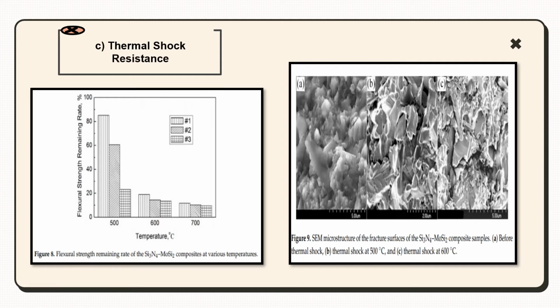As demonstrated in this figure, microcracks could be clearly observed when compared with the samples without thermal shock experience. In addition, the quantity and size of the microcracks increased with increasing thermal shock testing temperatures, which resulted from the internal stresses due to the thermal expansion mismatch. As a result, the flexural strength decreased with an increasing internal stress and thermal mismatch of the two main constituents.